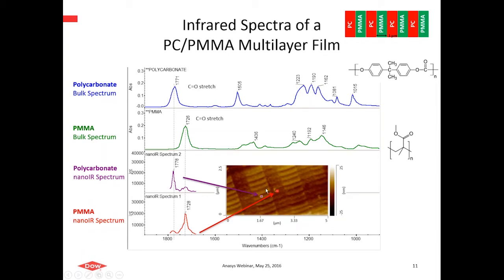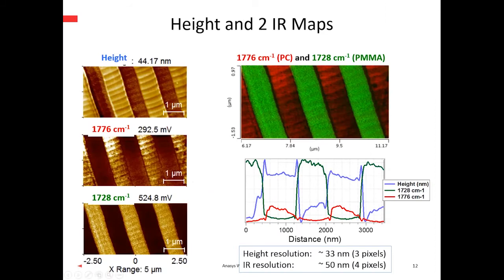And as Craig mentioned, now we can sit at either one of these absorption peaks and collect a map. We'll show that here. So we've got height imaging at the top, and then now we have maps representing the carbonyl from the polycarbonate in the middle and then from the PMMA below. These two maps can be pseudo-colored and overlaid, and that's shown in the upper right. And you can see we have very good edge resolution of these two immiscible polymers. And if we take line sections across them and do some average profiling, we show that in the middle.